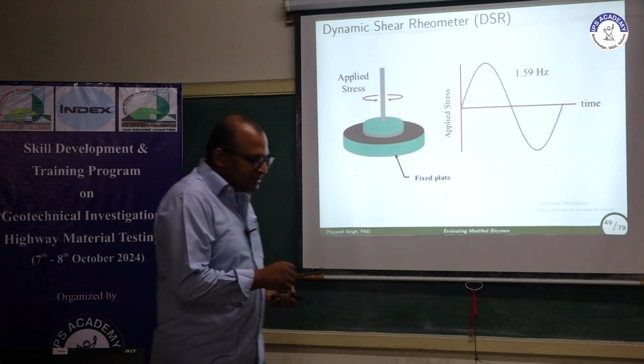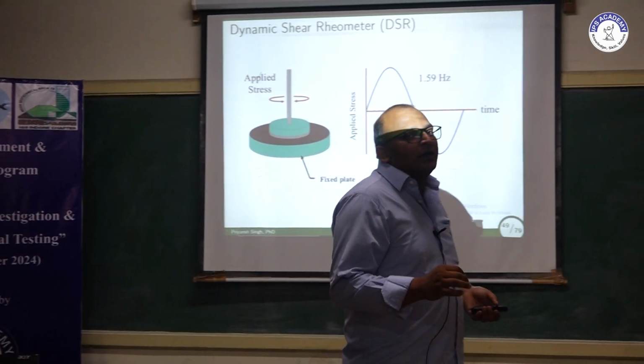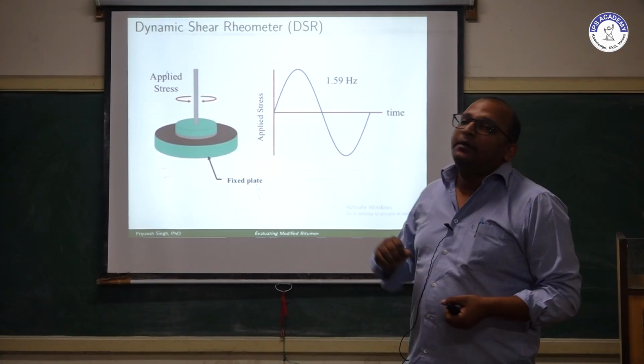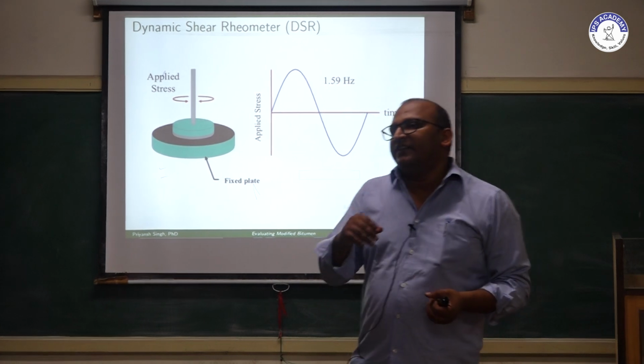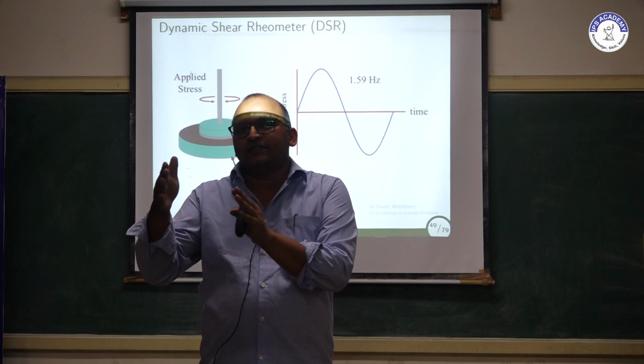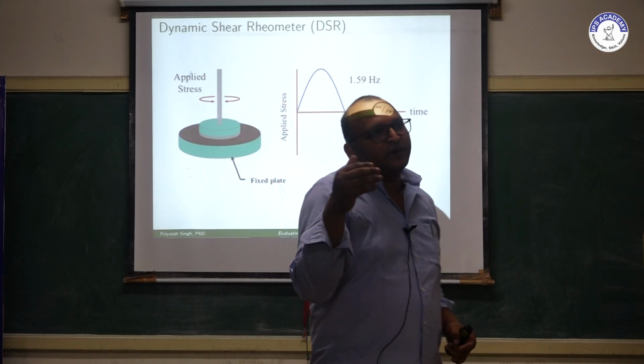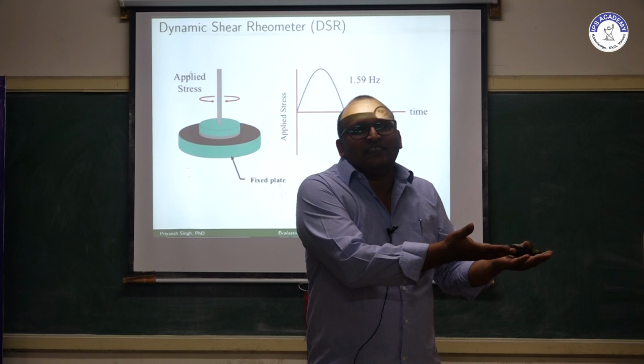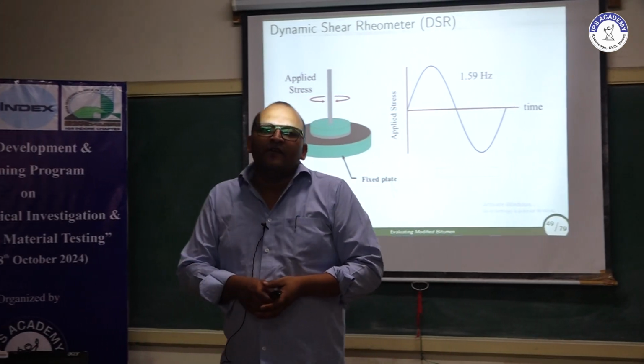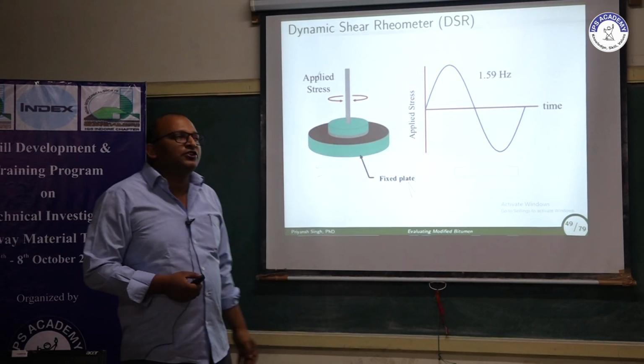Then the next biggest improvement is being brought in the form of the dynamic shear rheometer. Now what we have discussed is that at service temperature, our binder behaves like a viscoelastic material. A viscoelastic material has both properties partially. It can behave as a viscous material and also as an elastic material. So in order to characterize that viscoelastic nature, this DSR testing is introduced.